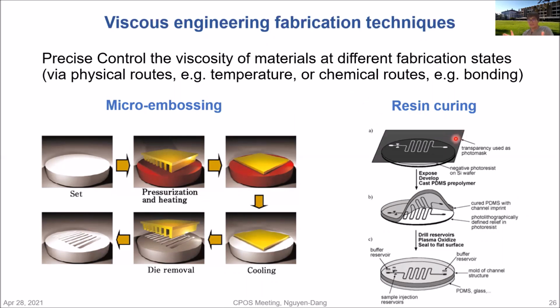The viscosity can be controlled also by chemical routes, for example, by resin curing. If you work with PDMS, you know that you can pour PDMS in liquid form on the mold, on the stamp, and then you just cure it, create chemical bonding, and then you change the viscosity. After curing, the viscosity is extremely high and there's no deformation.